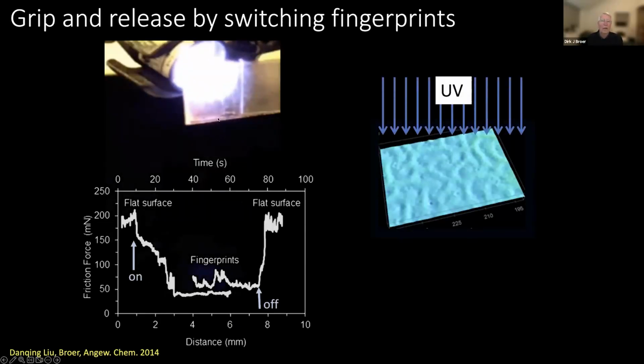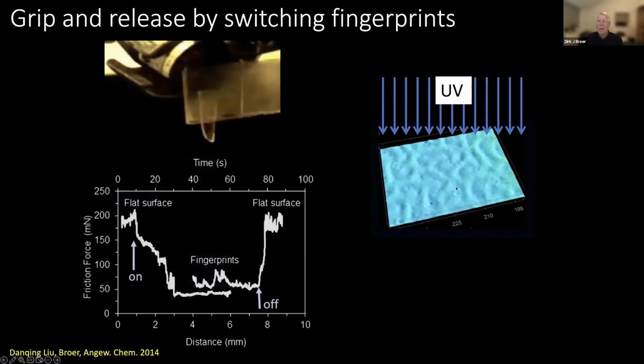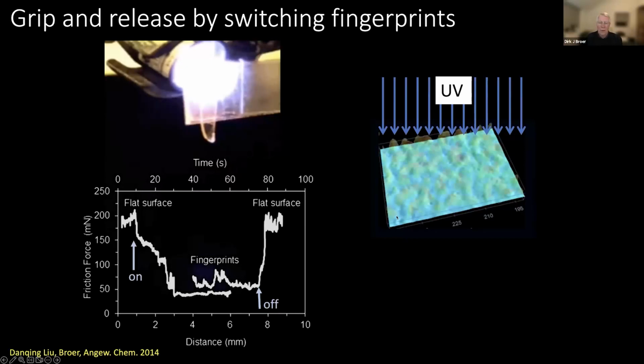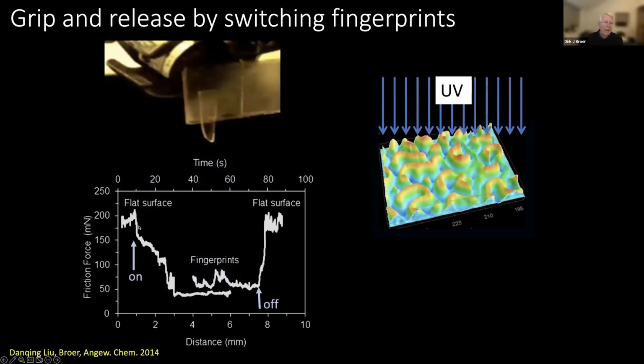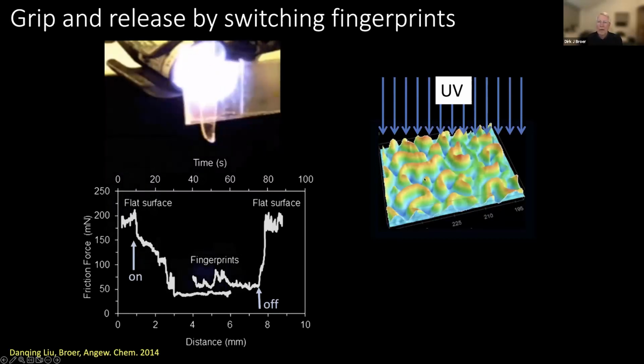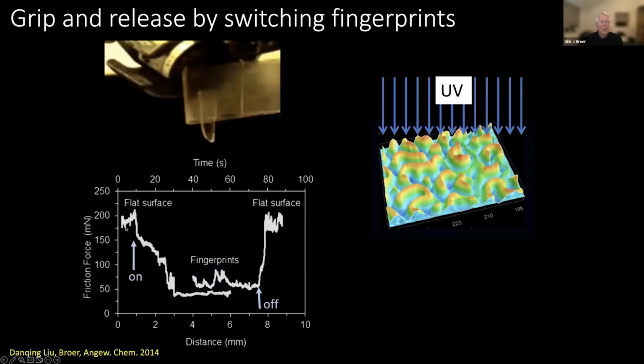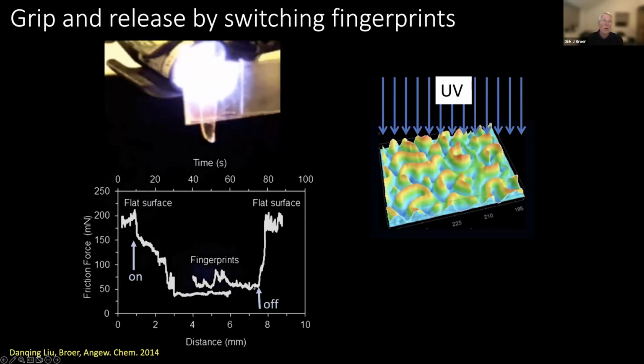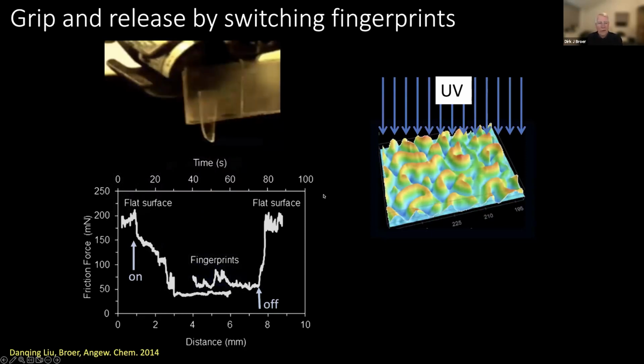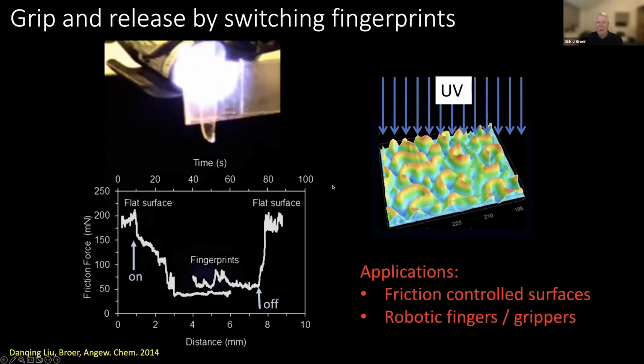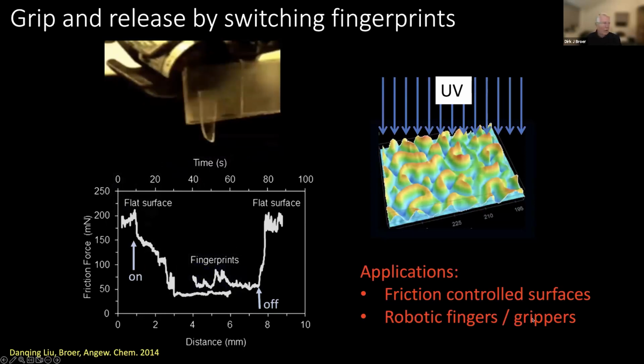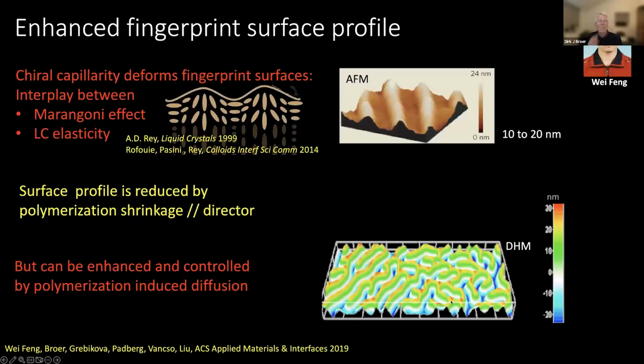So here we have an object which is embedded in between the two plates with the fingerprint forming surfaces. In the flat state, you'll have a high friction coefficient, but because of the regularity of the system, the contact area of the contacting surface is reduced, and you are also reducing the friction coefficient to a much lower value. And by doing this, the two plates which are holding this object are releasing the object that you expose them with UV light. So the first application could be friction-controlled surfaces or robotic fingers and grippers in this case.